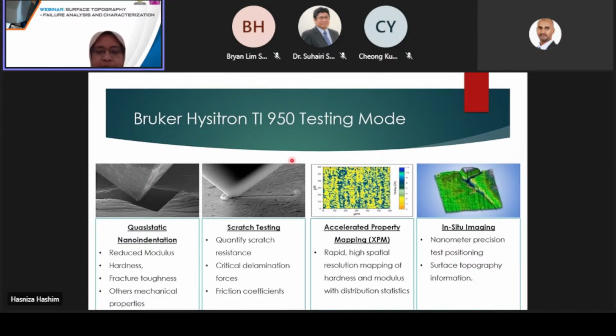These are the main modes available on our Bruker TI-950. We have quasi-static nano indentation, which most people just refer to as nano indentation. The commonly measured properties through nano indentation are elastic modulus and hardness. However, the technique can also be used to extract other information like fracture toughness or other mechanical properties. There is also a scratch testing mode, which can be used to determine properties like the coefficient of friction or adhesion properties of a film on a substrate, if you have failures like delaminations.